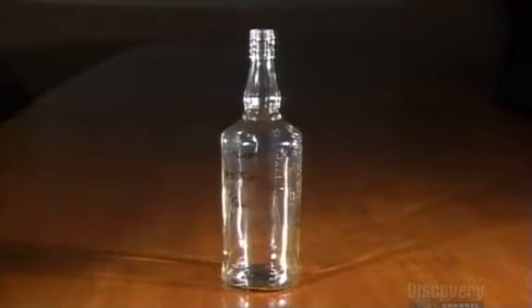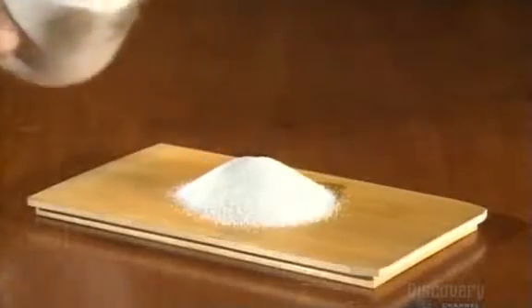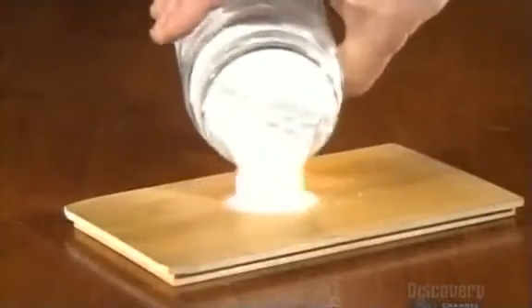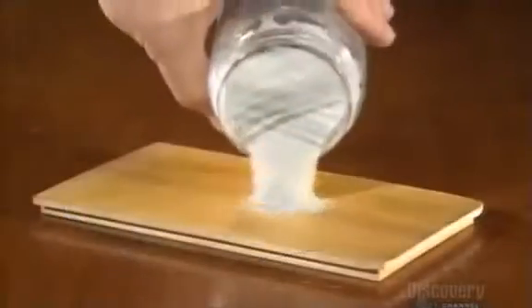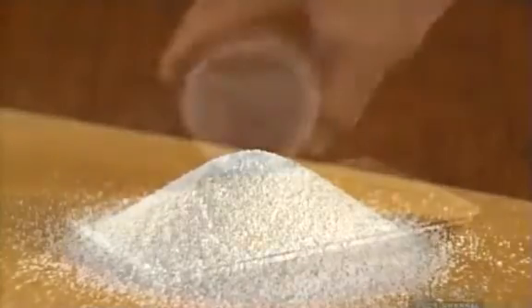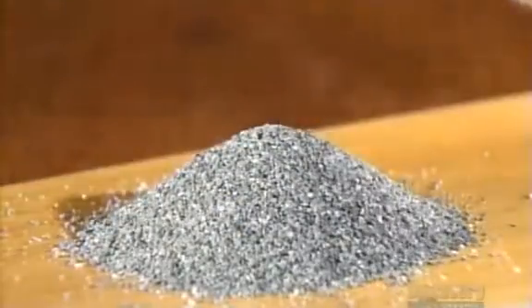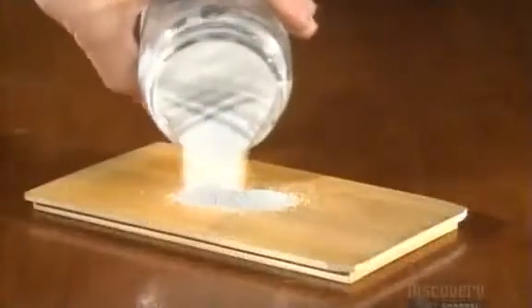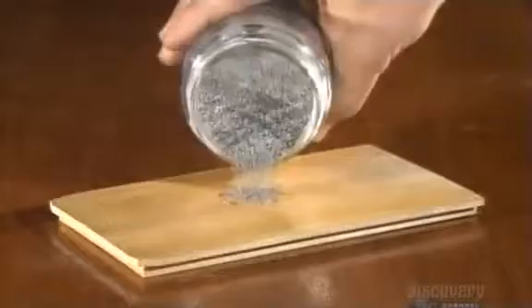The recipe for glass combines about half a dozen natural raw materials, but the main ones are silica sand, soda ash, and limestone. Silica sand usually makes up about 70% of the batch. The soda ash helps melt the silica evenly. It comprises about 15%. A limestone content of about 10% makes the finished glass more durable. They combine these ingredients with recycled glass called cullet.